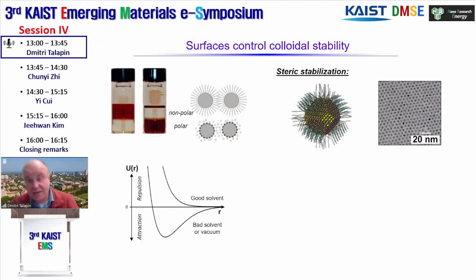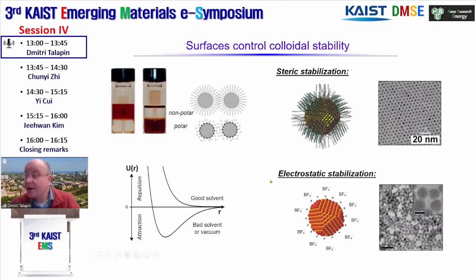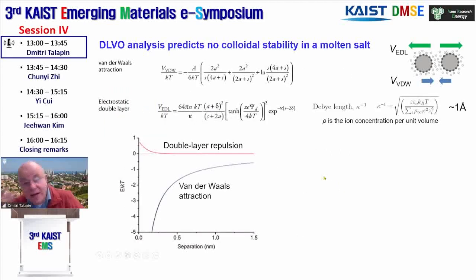So there are two ways to impart colloidal stability. One is steric stabilization, when we attach to the surface molecules with a large number of configurational degrees of freedom, and they impart osmotic forces, acting as a repulsive part of pair potentials. If we put particles in polarizable media, we typically rely on so-called electrostatic stabilization, where we attach charged groups to the particle surfaces, and they impart electrostatic repulsion. Now, in molten salts, we don't have anything that looks like polymer brushes to install steric repulsion, and it's a very polarizable medium, so we need to rely on analysis previously developed for colloidal stability in polar solvents.